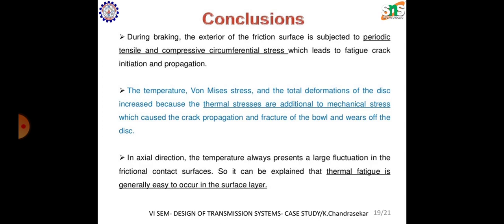Then I would like to conclude that during braking, the exterior of the friction surface is subjected to periodic tensile and compressive circumferential stress, which leads to fatigue, crack initiation and propagation. The temperature, von Mises stress and local total deformations of the disc increased because the thermal stresses are additional to the mechanical stress, which caused the crack propagation and a fracture of the disc and wear. In the axial direction, the temperature always presents a large fluctuation in the frictional contact surfaces. So it can be explained that thermal fatigue is generally easy to occur in the surface layer.